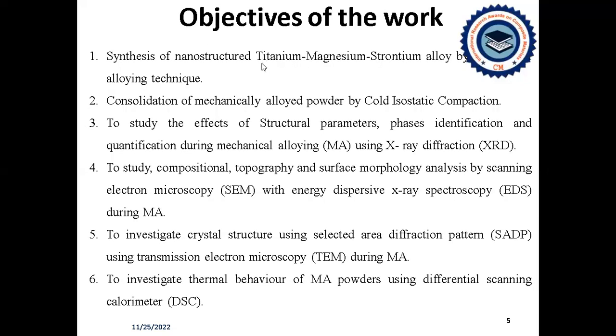And the objectives of the work go like this. The first is to synthesize the nanostructured titanium, magnesium, strontium alloy by the mechanical alloying technique, and consolidate the alloyed powder by cold isostatic compaction, to study the effects of structural parameters, phase identification, and quantification during mechanical alloying using the XRD technique. Also, to study the alloy powder's compositional and surface morphology, scanning electron microscopy with energy dispersive spectroscopy is examined during mechanical alloying.